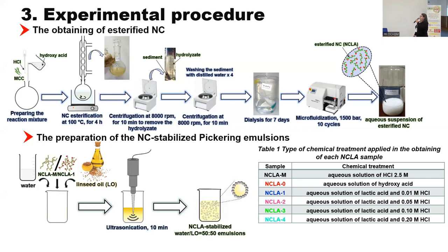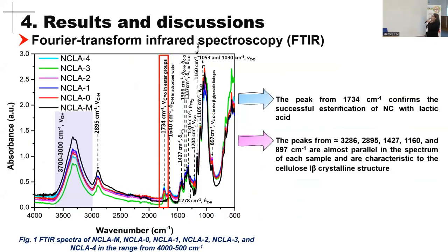The Pickering emulsions were simply obtained by mixing equal volumes of linseed oil and water that contain 0.5 and 1% per weight nanocellulose, followed by ultrasonication. The FTIR spectra showed that regardless of the presence of the hydrochloric acid in the reaction media, all the samples that were obtained by treatment with lactic acid present a new peak at around 1,734 cm⁻¹, which is characteristic to the C=O stretching vibration from the new ester groups that were formed on the surface of nanocellulose.